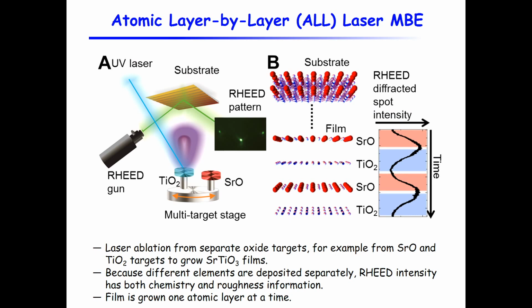And what we have been pursuing is to use separate targets. Instead of strontium titanate, for example, we use titanium dioxide and strontium oxide targets. And we just switch the target in front of the laser back and forth, so that on the strontium titanate substrate, we first put down a strontium oxide layer, followed by a titanium oxide layer. And because all these different elements come separately, the intensity of the RHEED spots reflects both the chemical information as well as the roughness information. Right? And with this, we can monitor the deposition so that we cover the whole atomic layer of strontium oxide before we switch.